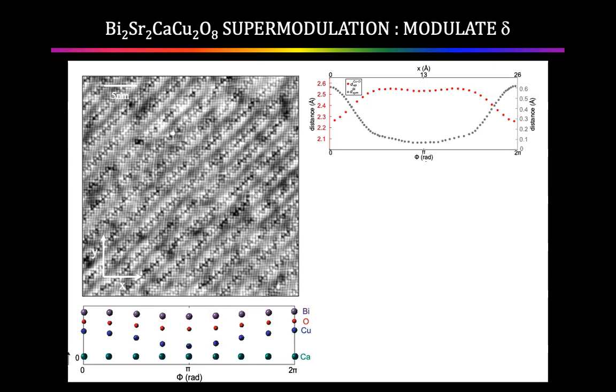So from the refinement, when the bismuth atom is at maximum vertical displacement, the apical to copper distance is 2.2 angstroms, 2.25. And when the bismuth atom is at its minimum displacement, the apical distance to copper is 2.5. So the key atom is moving around in the unit cell by 0.3 angstroms in a unit cell of size less than 4 angstroms. If you know something about material science, those are massive distance changes for the location of the atom in the unit cell, 10% of the unit cell.